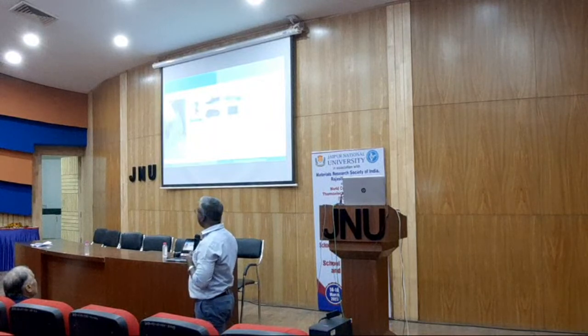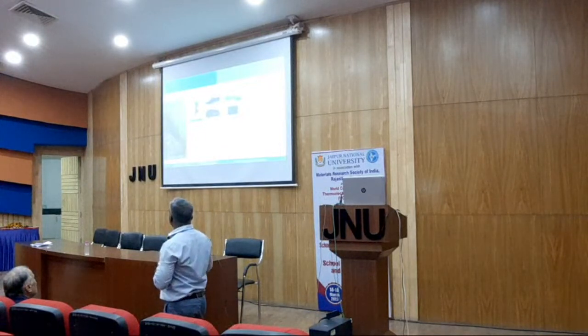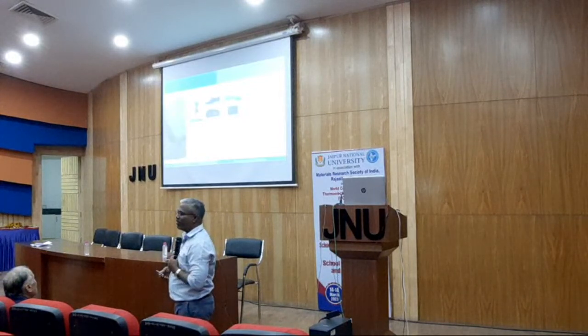And then the final outcome is that when people are stepping, it gives 20 millivolt, and whenever people go up and down a staircase, it gives almost 60 millivolt. The 60 millivolt was the highest we received, on 12 pairs of PN junctions of the devices, which can give the highest voltage. It's a macro size of the material. This is the way we did it: whenever the person walked, it could be measured on the portable CRO data, with continuous monitoring.